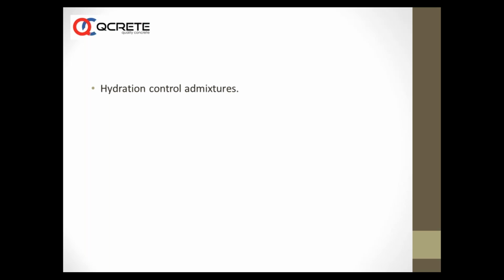This is very useful in high cement content mixes, low water-cement ratio mixes, where some cement particles sit unhydrated for a long time due to various reasons - one being a very low amount of water that has evaporated. In such cases, these hydration control admixtures will not allow water to escape. They control the rate of hydration so it continues continuously, and also act like a catalyst to change the process of hydration, accelerating it over a period of time.